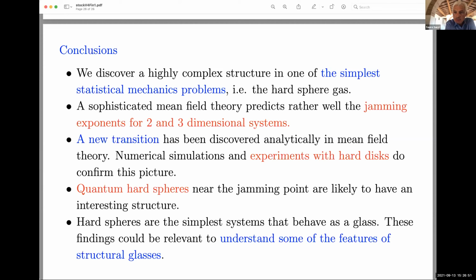So unfortunately, as I told you, we are not able to compute exactly the dimension at which you can start to do an epsilon expansion. The fact that the results are very good in dimension 3 and reasonably good in dimension 2 suggests that the dimension where you start to compute the correction may be something around 2 or 2.5, I don't know. That is the part that we have to really do the computation. However, this is a different story. So what happens here is that for some reason, for this type of system, we have been very lucky that we find a system in which the corrections to mean field theory are very small.